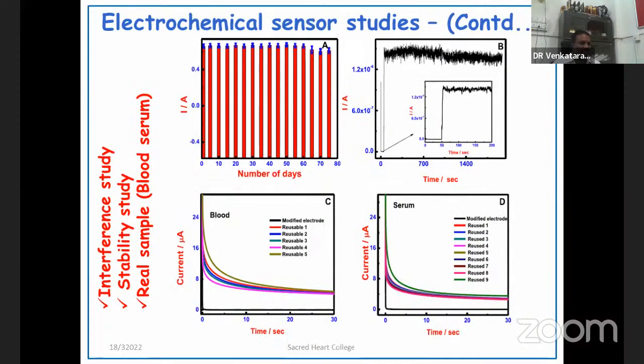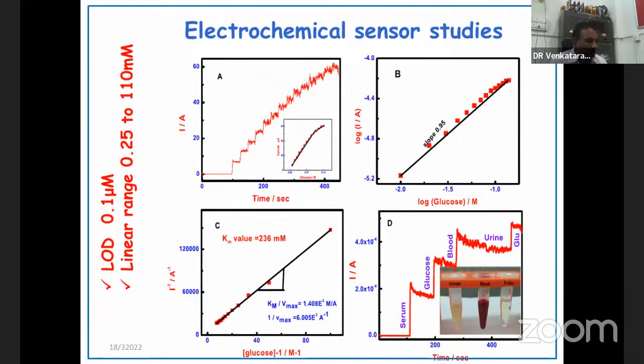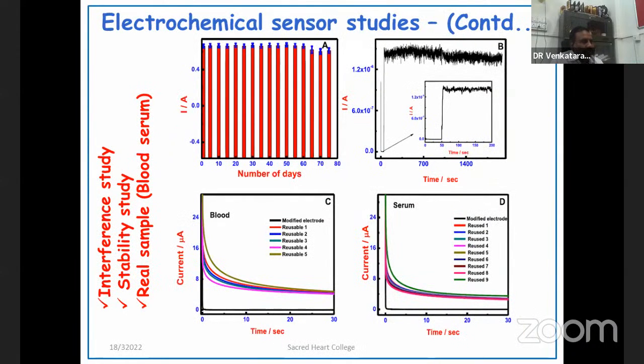So that capacitance current should be eliminated using other materials. For that, we also used graphene and graphene oxides. Once you fabricate, you have to quantify and describe all your sensor features, like the linear range. From the linear range, you can estimate the lower and higher concentration limits and the reproducibility factor. And of course, you have to check the biocompatibility and interferences. Interference means along with glucose, things like ascorbic acid, uric acid, and amino acids present in your blood sample. You have to eliminate the reactions of other analytes in the presence of glucose, so that you selectively detect glucose using your sensor device.